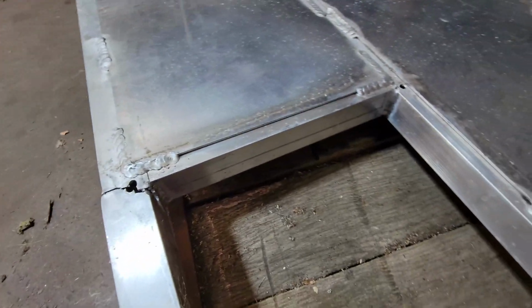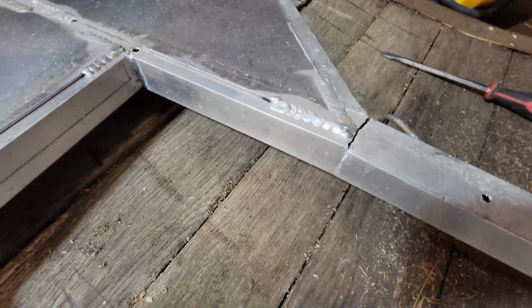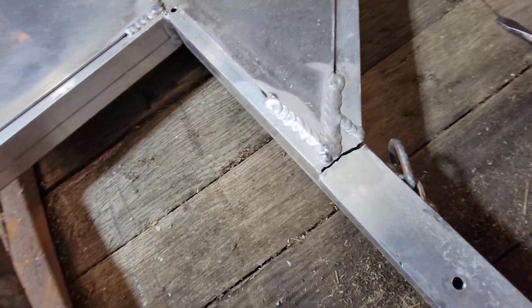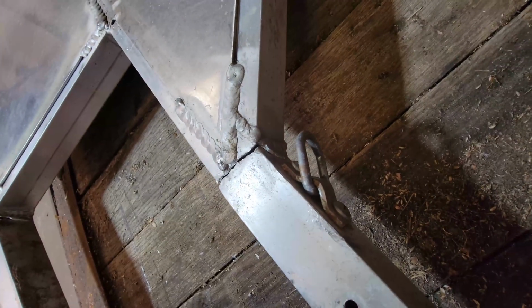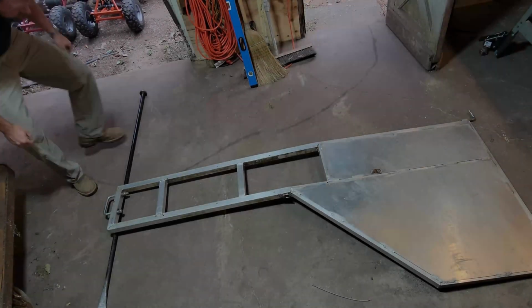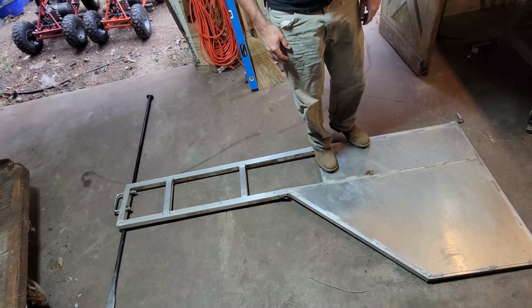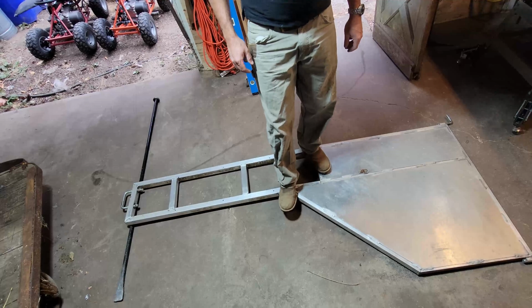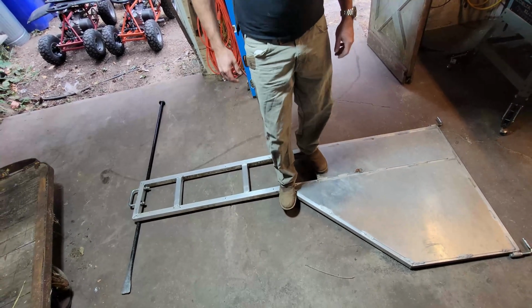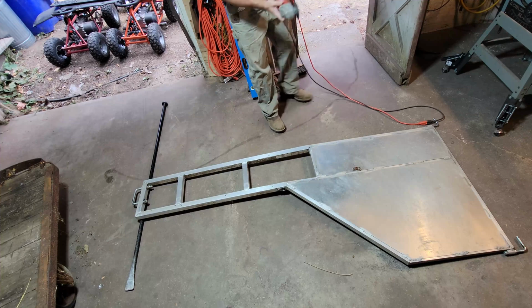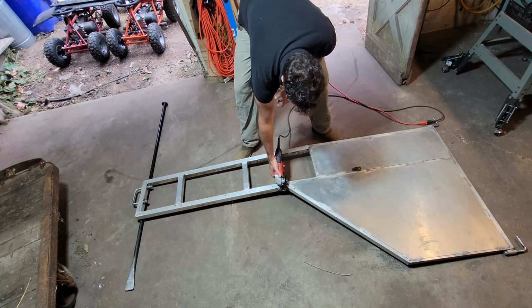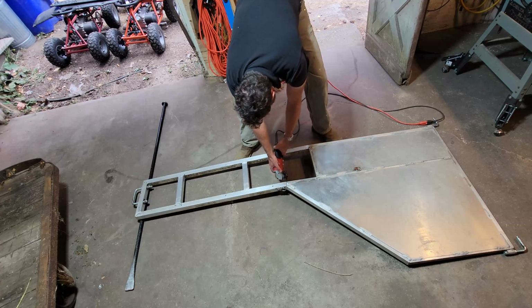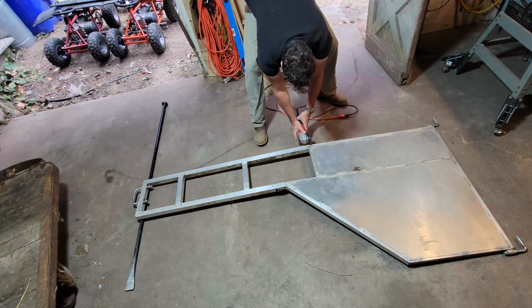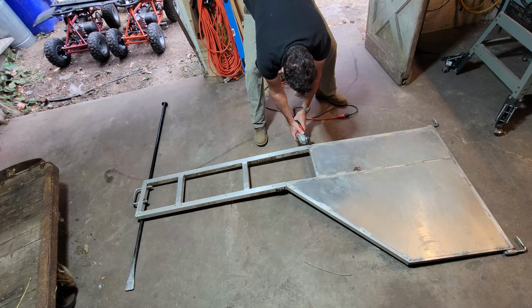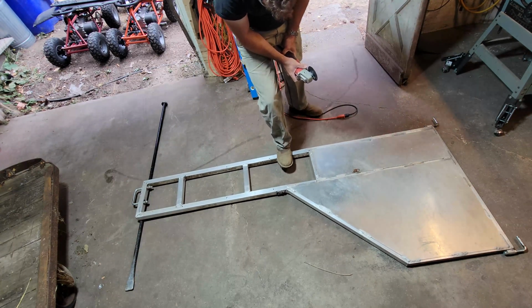It's now that the true extent of the crack is visible. Simply use my crowbar to try and bend the gate back into place. However, as the aluminium has cracked, it has also deformed and extended, resulting in excess material stopping this gate from bending back straight. I use my angle grinder with a slitting disc to cut out the excess material to allow the gate to bend back straight.